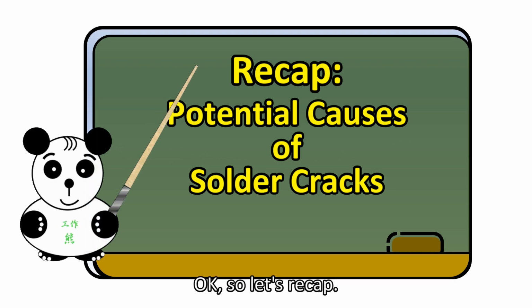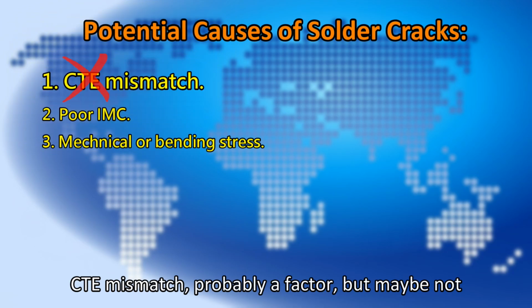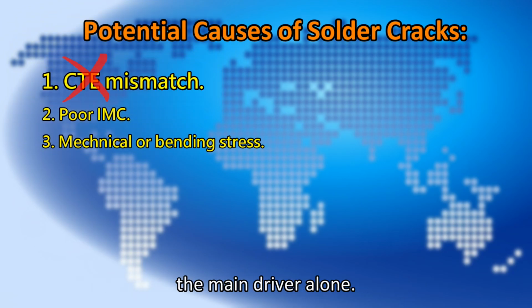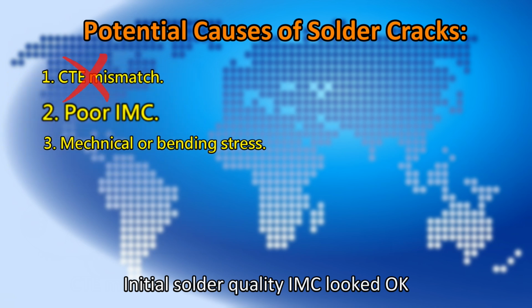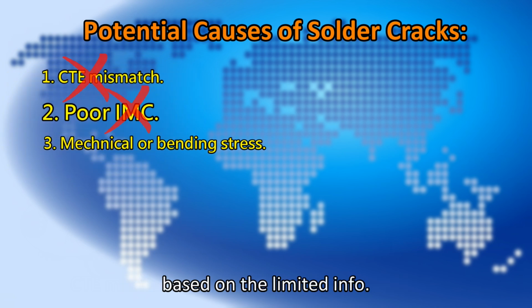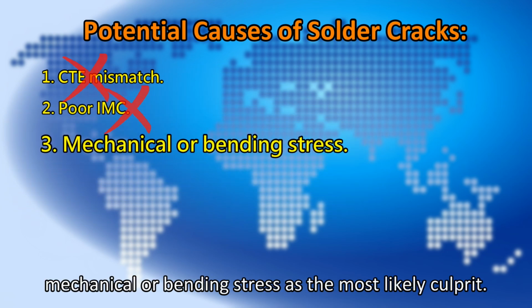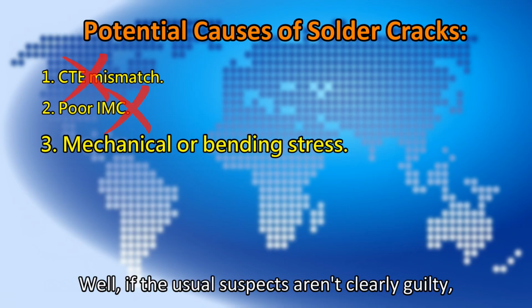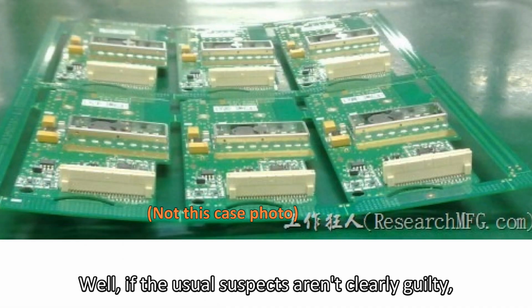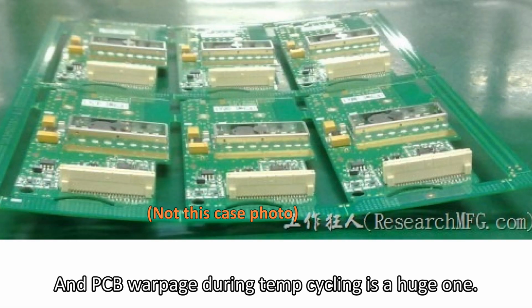Okay, so let's recap. CTE mismatch. Probably a factor, but maybe not the main driver alone. Initial solder quality, IMC, looked okay based on the limited info. So where does that leave us? The source material strongly suggests mechanical or bending stress as the most likely culprit. Why that? Well, if the usual suspects aren't clearly guilty, you look for other forces. And PCB warpage during temp cycling is a huge one.